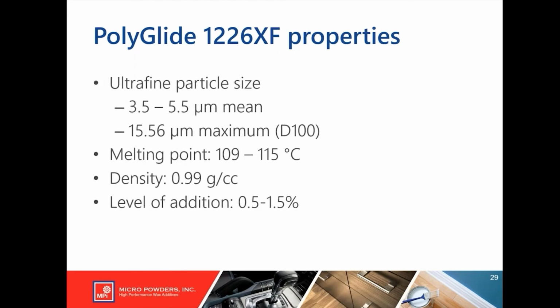So this product is designed as a very small particle, so about 4 micron mean, 15 microns maximum. This allows it to be used in a lot of end applications, thin film coatings where you don't want to affect the gloss too much. The melting point of this product is based on the high density polyethylene, so it's about 112C. The density is 0.99, so that's pretty good. So that's a good density to get the particle up to the surface efficiently. And typically for almost all of our high performance additives, you're dosing 0.5%, 1%, maybe 1.5%.